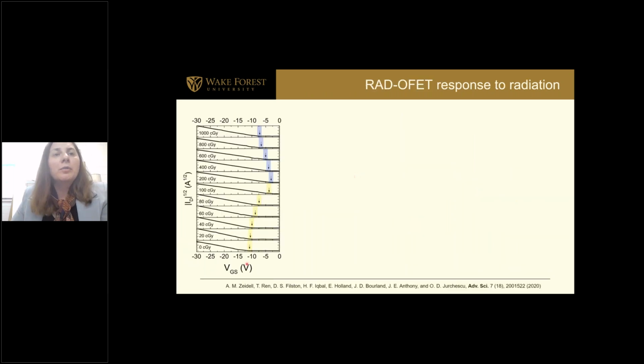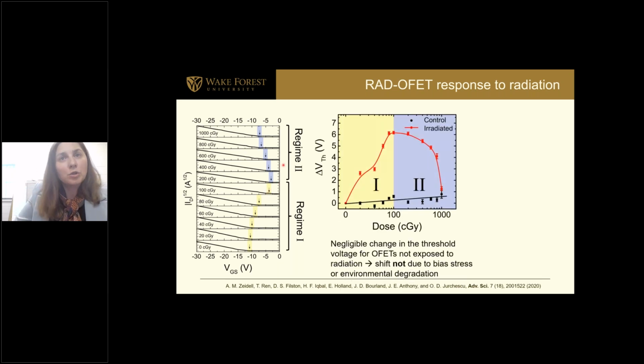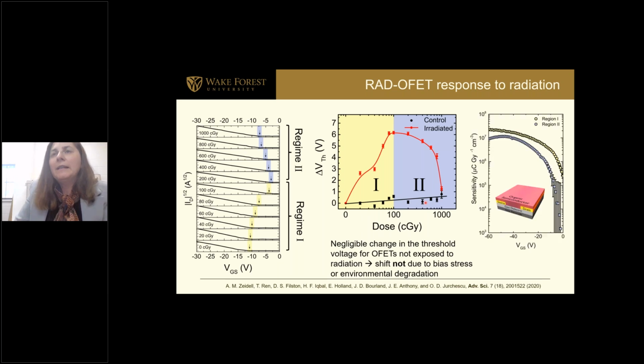So if we follow the shift as a function of dose, you see that first we have the threshold voltage becoming more positive and then more negative. So clearly there's two things going on. Here in red, you see the overall shift as a function of radiation dose. And then in black, we see the control sample. This is the sample that my student took in the backpack, exposed, and then measured again. The sensitivity is increased with the gate voltage.